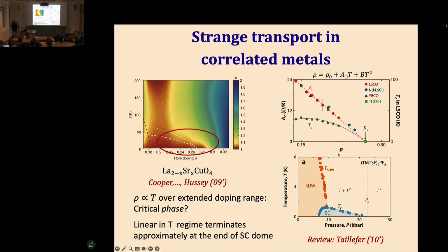And moreover, here's similar behavior in an organic superconductor, which is also an unconventional superconductor, believed to be d-wave. But other than that, it's a completely different material, and you see also similar behavior. Here, the control parameter is not doping, it's pressure. You have a superconducting dome-like shape, and you have a linear T resistivity in the normal state. It looks like a combination of T plus T squared, and the coefficient of the linear T term disappears close to the critical pressure, where superconductivity also disappears.